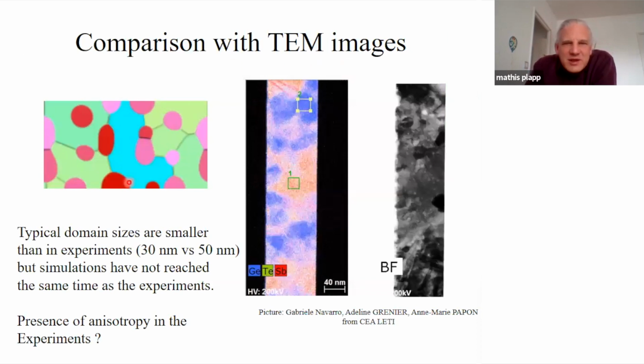And here's our final picture, and here's a qualitative comparison to the TEM picture. Unfortunately, it's rotated by 90 degrees, so here the film is vertical, whereas in our picture it's horizontal. You cannot say much more than, well, we have a polycrystalline two-phase material because there's too many approximations to have a quantitative description. We see that our germanium crystals are smaller than the ones in the experiments, but it's also because our simulation was not able to do the same duration of annealing as the experiments. And you can also see that obviously we are missing some things because the structure in the experiment seems to be much more anisotropic than in our simulations. Which is quite natural since we didn't put any anisotropy anywhere. Okay, so this is a sort of isothermal annealing.